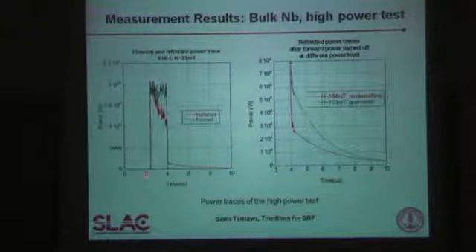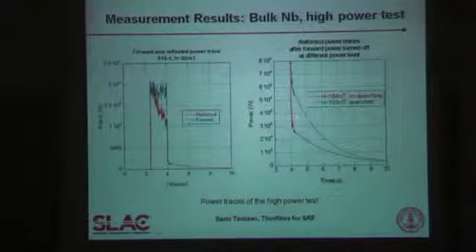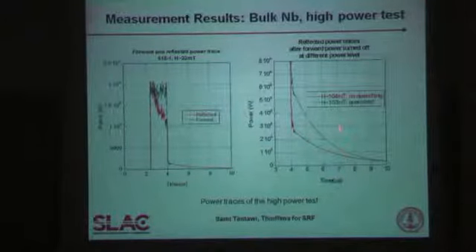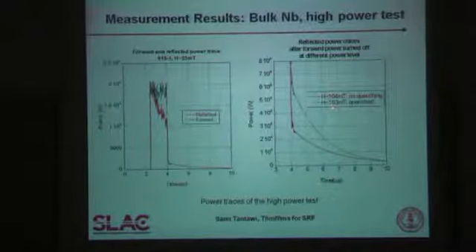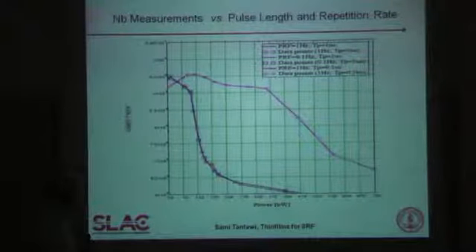This is a typical measurement at low level. There is some serious noise at this level. This shows a sample before quenching and after quenching. At the red line the system still has a very long tail, but after going to a rather high field — like 135 millitesla on this particular niobium sample — the decay length becomes very fast, and we can distinguish that the cavity starts to quench and measure the quality factor.